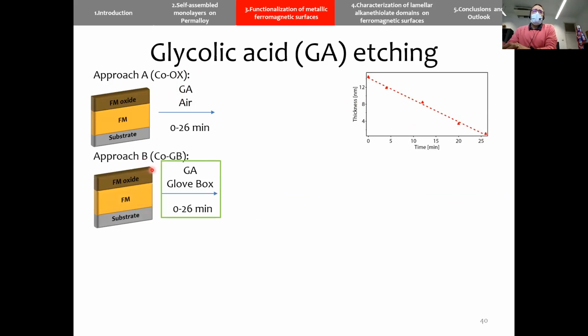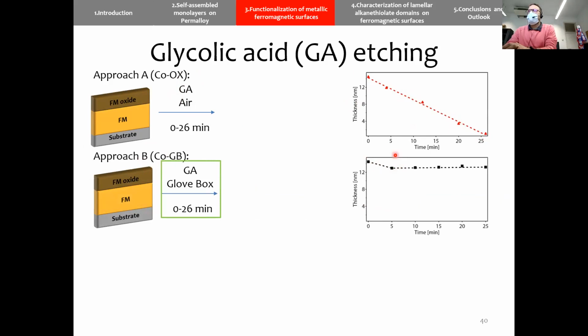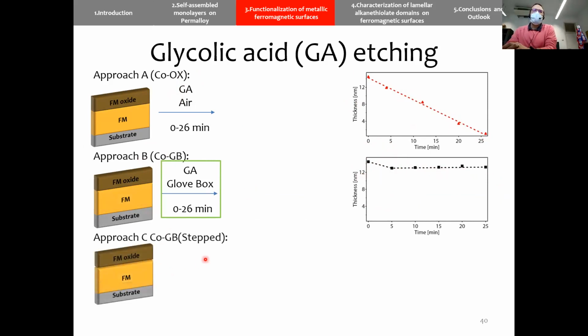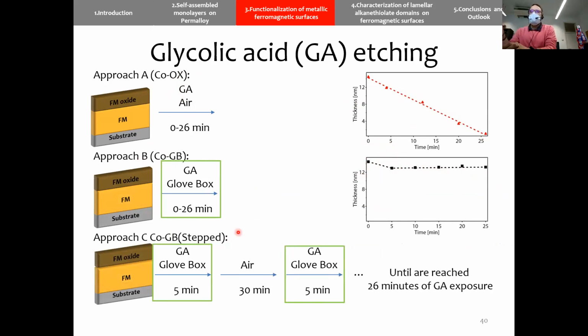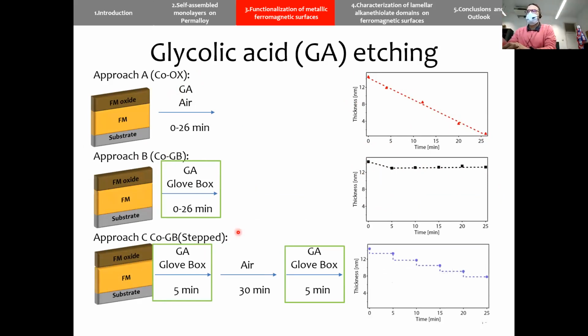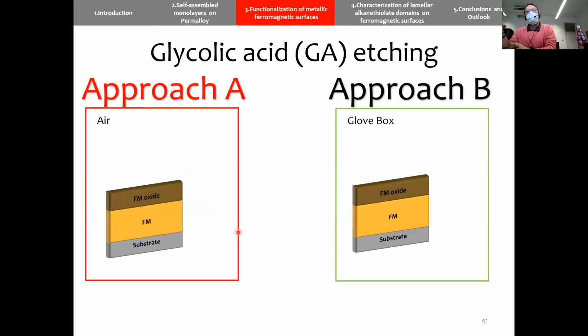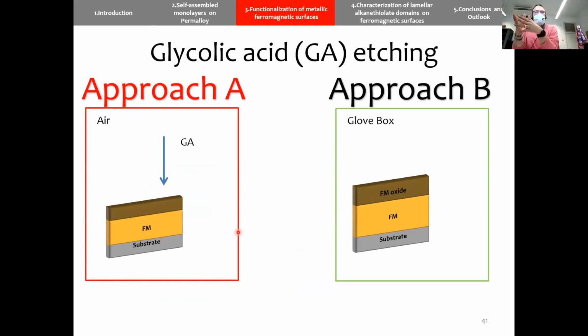In approach B, we were using a glove box, and we saw that, yes, after a first jump, this thickness is maintained. And then we started cycling between glove box and air until the 26 minutes were reached. And in this case, we see a clear staircase behavior. So our hypothesis is that if we perform the etching in air, the glycolic acid attacks the oxide, the metallic surface reoxidizes, and the glycolic acid continues attacking until all the substrate is etched, all the ferromagnetic material is etched.